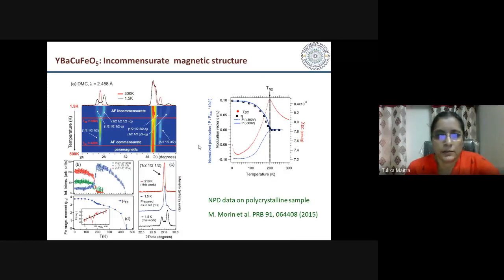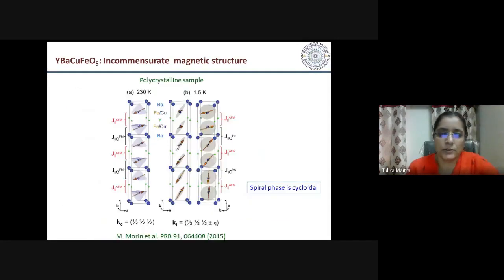And further, the incommensurate phase was also determined by Morin and others from neutron diffraction experiment, where I'll show what kind of incommensurate structure they found. But in the incommensurate phase, they also find that there is a finite polarization. Okay, so this incommensurate magnetic phase is also ferroelectric, is what their observation is. So this is the incommensurate magnetic structure. What they see here is that there is a spiral magnetic structure. When we go along C direction, the spins are canting away from each other, and then they have a spiral phase.